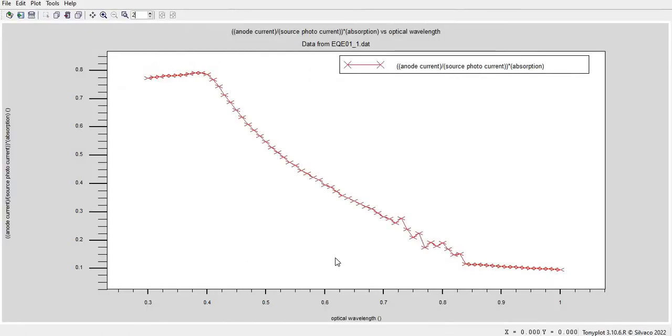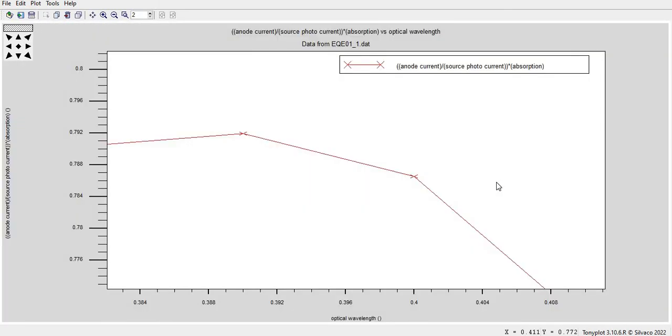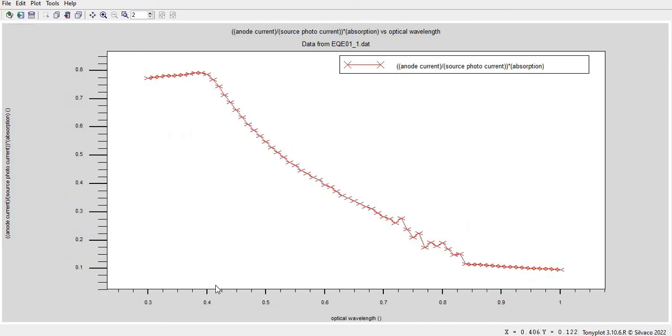And then I will show you EQE what I got. You can see here it is a maximum at almost 0.8 and you can say 80 percent almost. It is reaching 80 percent at the 0.4 or you can say 400 nanometer it is reaching the peak.